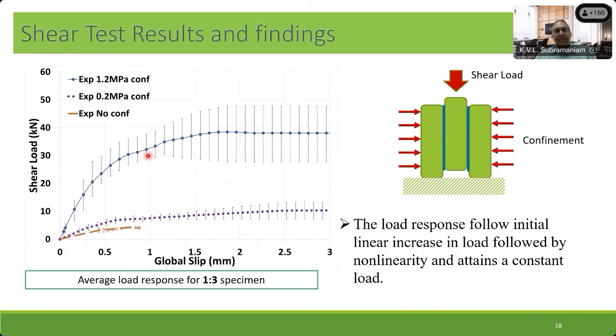And as I increase the confinement, you see that a larger amount of shear can be transmitted from the middle brick to the two side bricks, which means basically the shear transferring ability, or the capacity of this mortar, increases with the confinement that you apply. Now, why is this even relevant? In a typical masonry wall, the confinement would come from the vertical loads. And the shear loading that we're trying to evaluate is something that you would expect when you're looking at the in-plane shear response of a masonry wall.